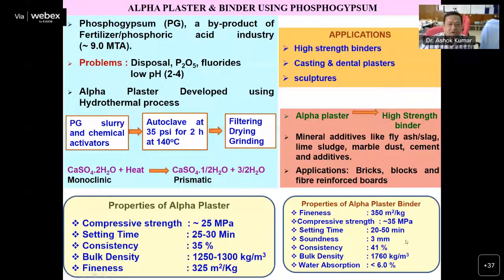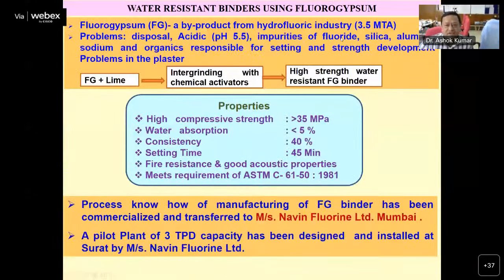The next binder which we have developed uses fluorogypsum. Fluorogypsum is a waste of the hydrofluoric acid industry, and it is acidic in nature. So first it has to be neutralized by adding lime, and then it is intergrinded with chemical activators for the development of the fluorogypsum binder. This binder also has very high strength of 35 MPa and low water adsorption.